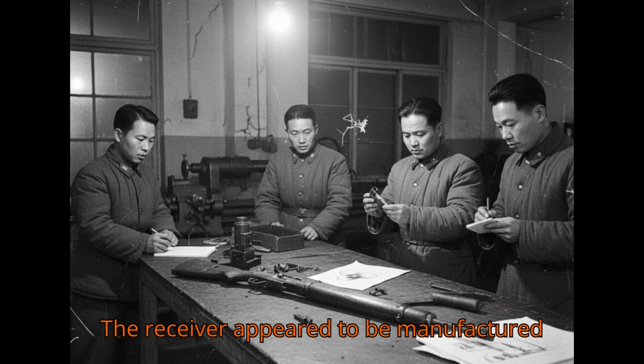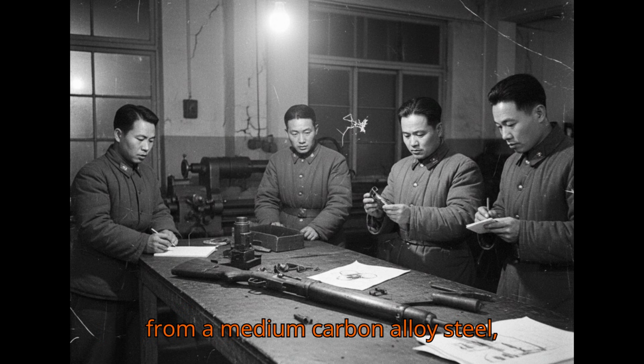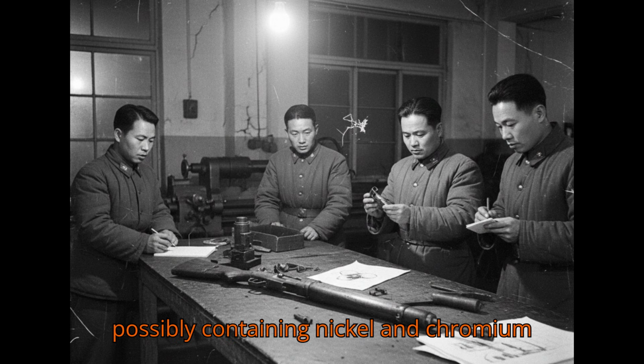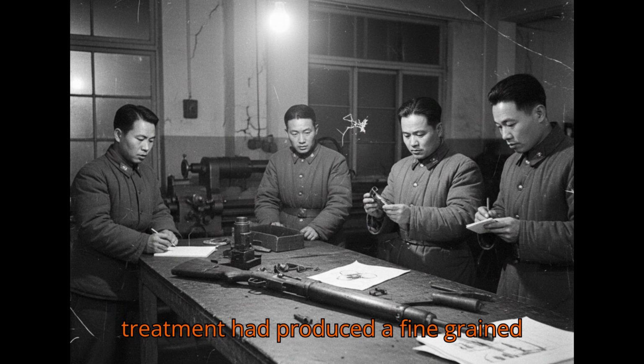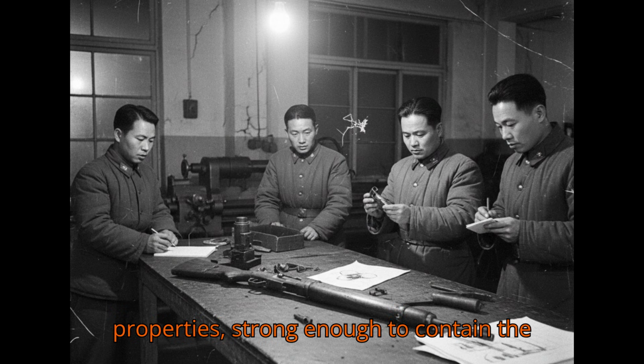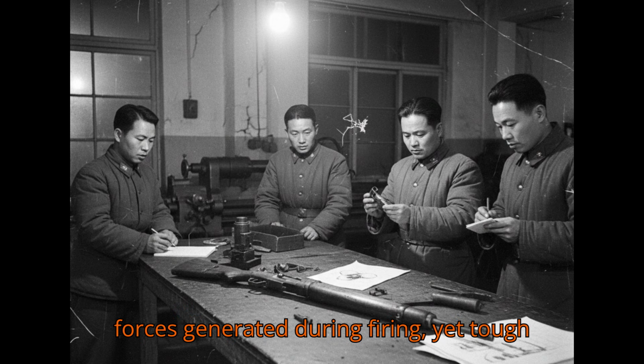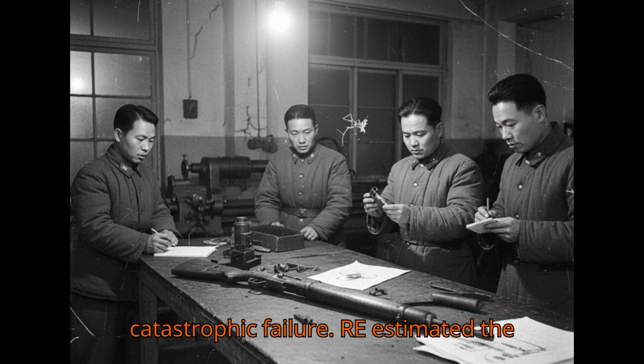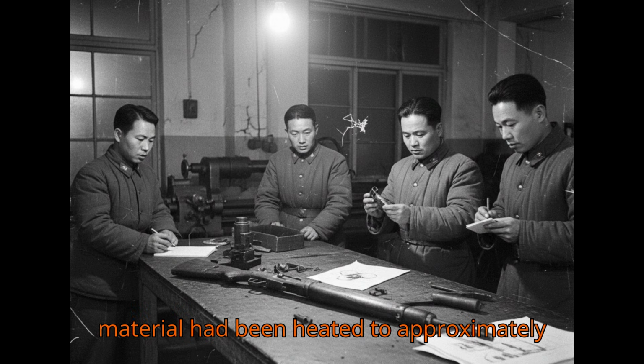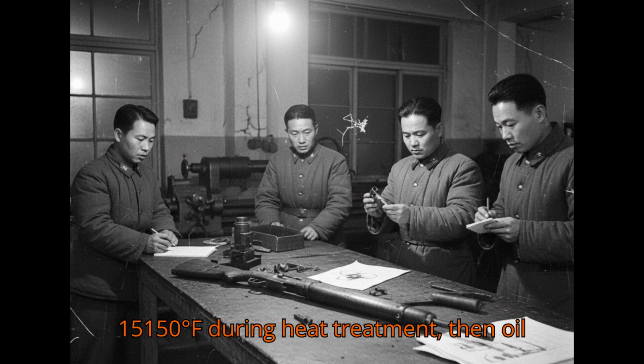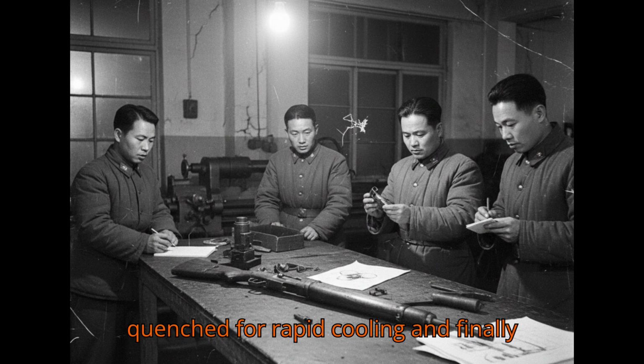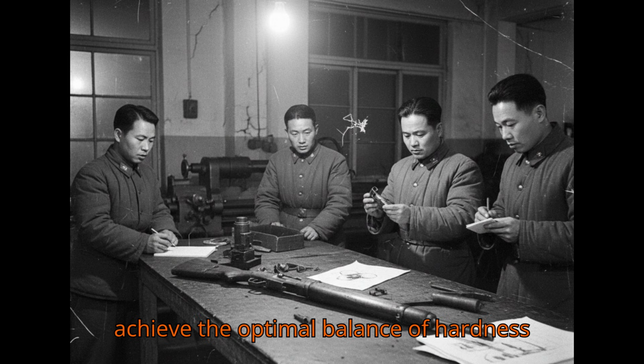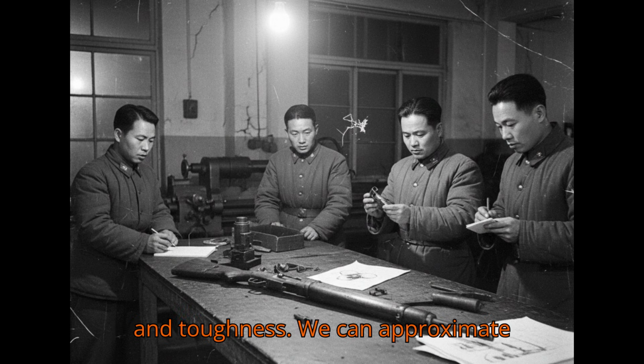The receiver appeared to be manufactured from a medium carbon alloy steel, possibly containing nickel and chromium for strength and toughness. The heat treatment had produced a fine-grained structure with excellent mechanical properties, strong enough to contain the forces generated during firing, yet tough enough to resist crack propagation and catastrophic failure. Ri estimated the material had been heated to approximately 1,550 degrees Fahrenheit during heat treatment, then oil-quenched for rapid cooling, and finally tempered at a lower temperature to achieve the optimal balance of hardness and toughness.